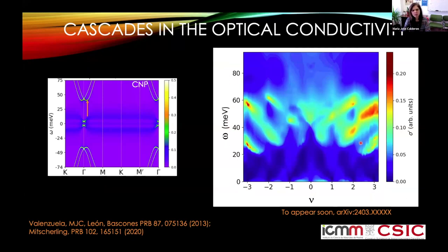So we can see that the optical conductivity has strong features happening at a range of energies that are given by the transitions between the flat and the remote bands. We have stronger peaks in these positions or these fillings at which we have a well-formed quasi-particle peak. And we have broader signals where there is more incoherence. Okay, and we can see also the resets and all these features that we can see very clearly in the density of states or the dI/dV from the STM measurements. But here we have another probe to see what is happening, and we hope that this kind of results can help us elucidate whether in the experiments we have these kind of features that we have observed.